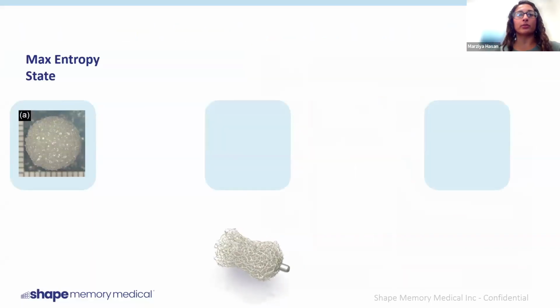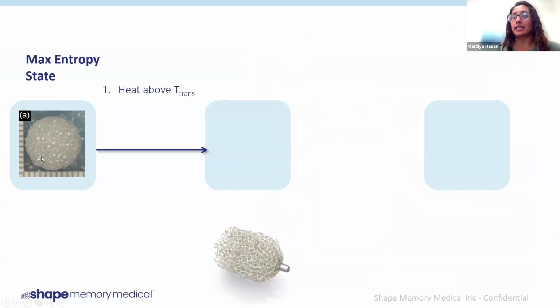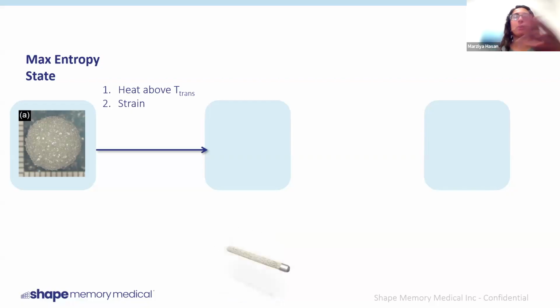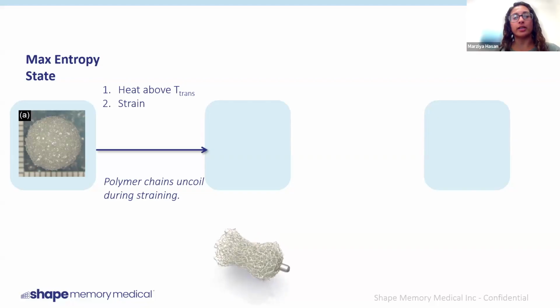Again, just going through the basic principles of SMPs. We have our material that we have made in some configuration. In this case, it's this shape A. We will heat this component above its transition temperature and apply some kind of strain to crimp it from this open cylinder to a smaller rod geometry. This will cause the polymer chains to uncoil while the strain is being put on, and we will hold this strain onto the material and cool it back down below its transition temperature.